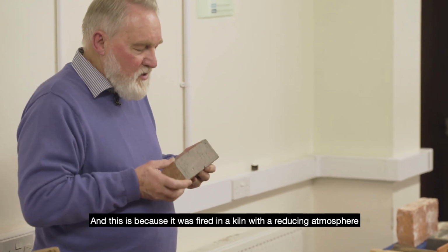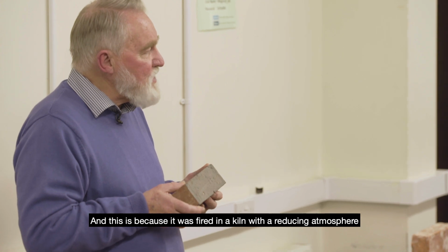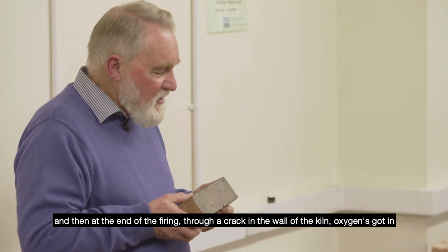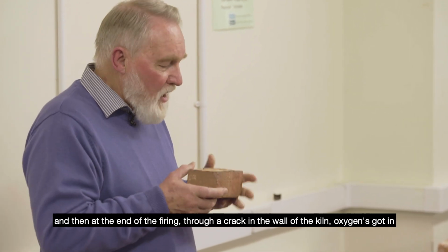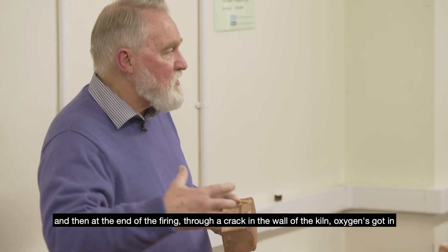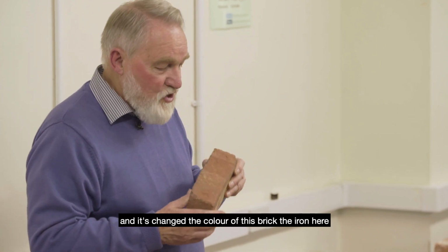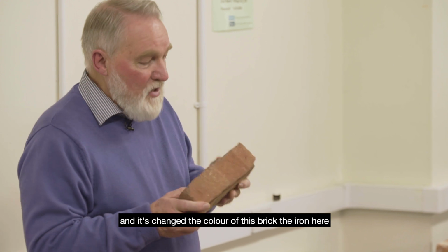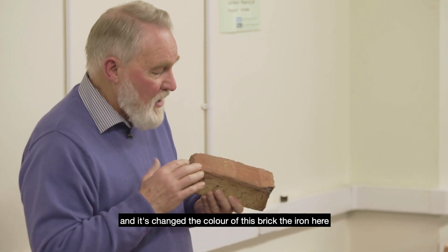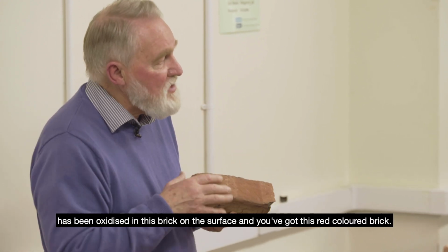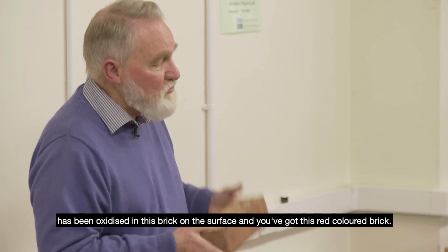And this is because it was fired in a kiln with a reducing atmosphere, and then at the end of the firing, through a crack in the wall of the kiln, oxygen got in and it's changed the colour of this brick. The iron here has been oxidised on the surface, and you've got this red coloured brick.